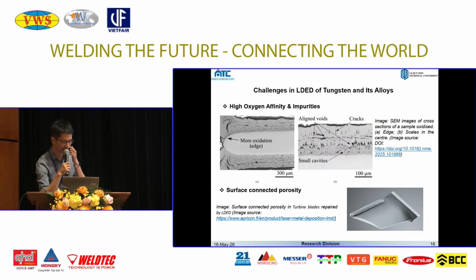Last but not least, tungsten has a very high oxygen affinity. That means it is very easy to oxidize in a non-inert environment. Tungsten reacts easily with oxygen at high temperature, forming oxides, and that weakens the grain boundaries and promotes cracking.